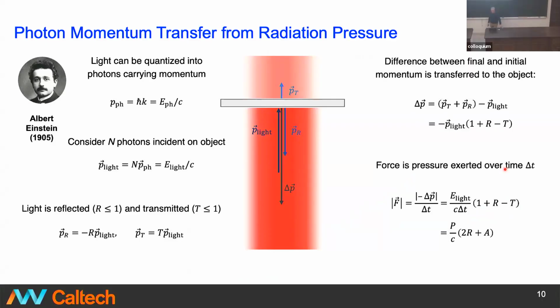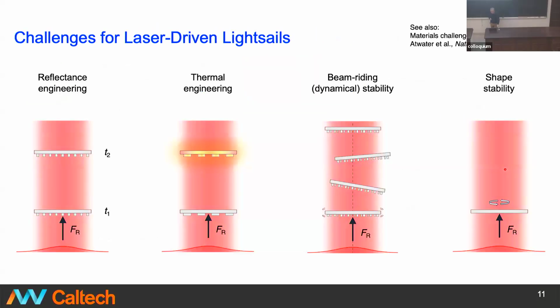So of course, momentum transfer results in radiation pressure that's proportional to the reflectance plus the absorbance of the material. It turns out that in this case, because we're using radiation pressure to propel something through space, we really have to pay close attention to absorption, because the only mechanism in space for managing the thermal load is through radiative emission. And that's going to dictate that the absorption be as low as possible. So there are some very interesting dynamics.